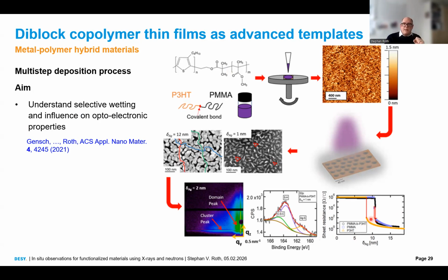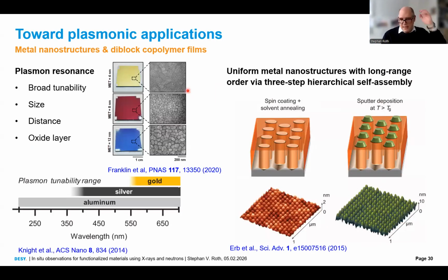Why selective wetting? When you ask what is the interaction between a metal and a polymer, the answer is: this depends. If you take gold, it reacts differently with polystyrene or with PMMA, polymethyl methacrylate. If you use silver, again, it's completely different, and so on. Especially when you look into all these fancy polymers which you use for solar cells, you actually have to experimentally deduce this interaction. This is what we are doing here, this interaction between the different metals. And as metals, as already indicated, I use gold, silver, and aluminum, because then I have a broad tunability of the plasmon resonance, and I can avoid or dedicatedly introduce oxide layers.